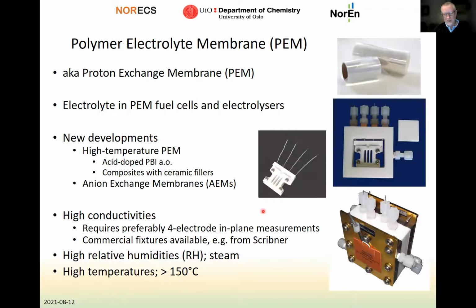When you test these membranes, they have high conductivities, and this requires preferably 4-electrode in-plane measurements. And there are many commercial fixtures available for this, for instance, from Scribner and other companies. Here you see one of them that we also use in my laboratory, where the membrane is fixed and pressed with these screws in between 4 electrodes. And this is placed inside the sample holder, and the electrodes are connected through here, and the whole thing is mounted in a PEM test cell that is supplied by Scribner in this case.